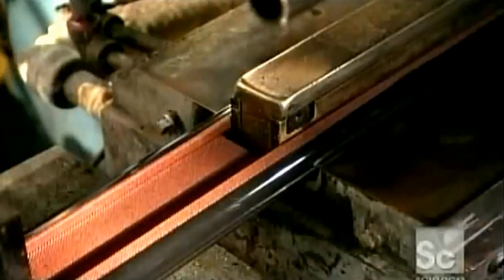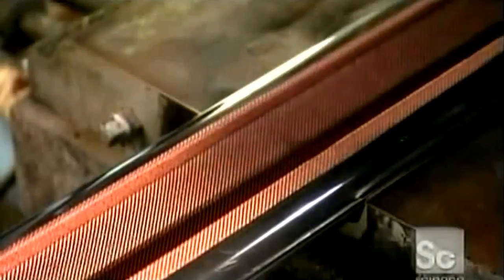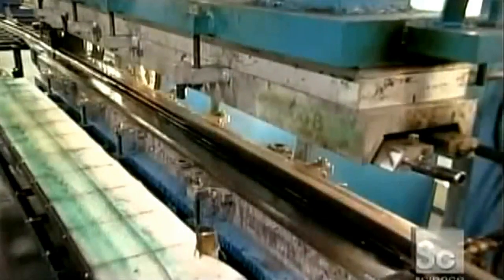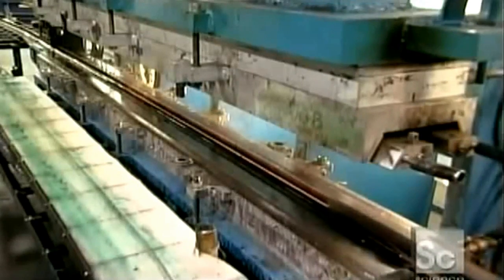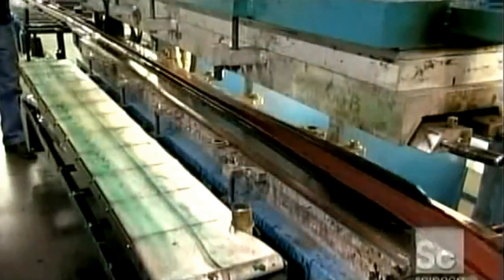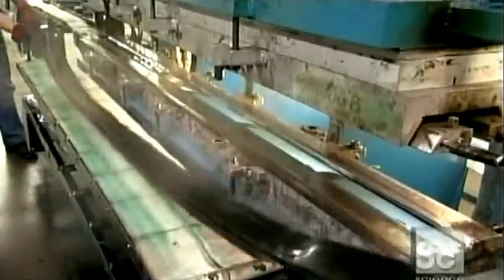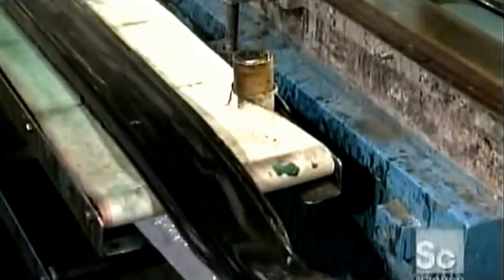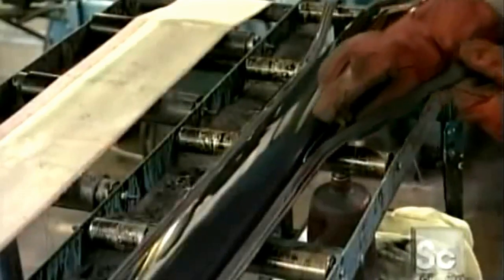10 to 15 minutes later, the mold lifts, and a chemical reaction called vulcanization has occurred. The layers have been laminated, and the handrail is now strong enough. The last step is to trim away the flash, or excess material.